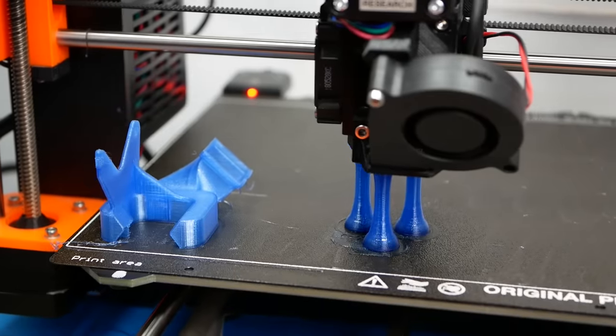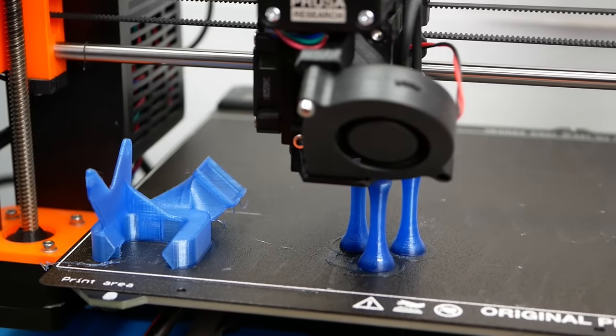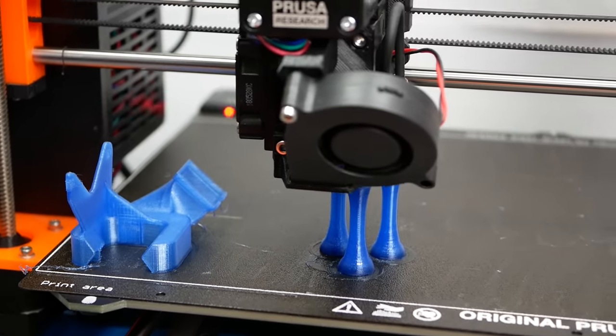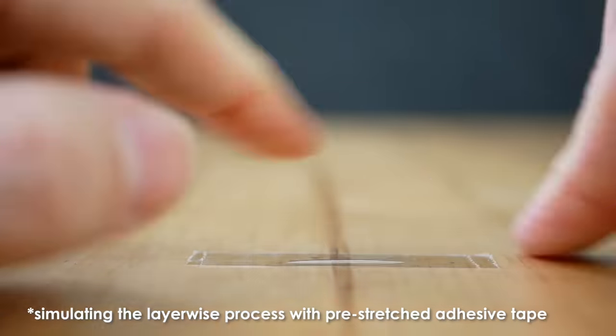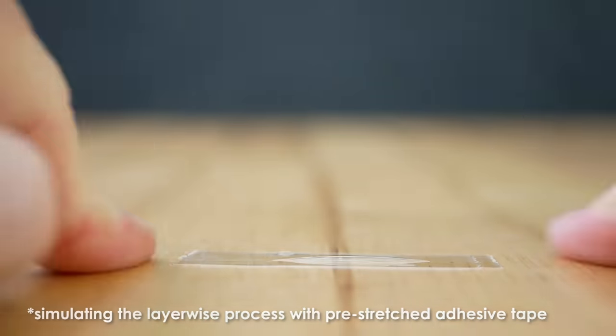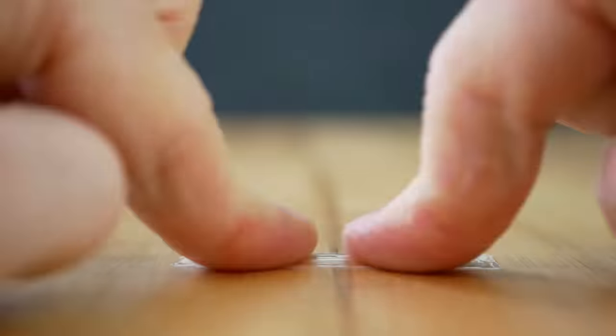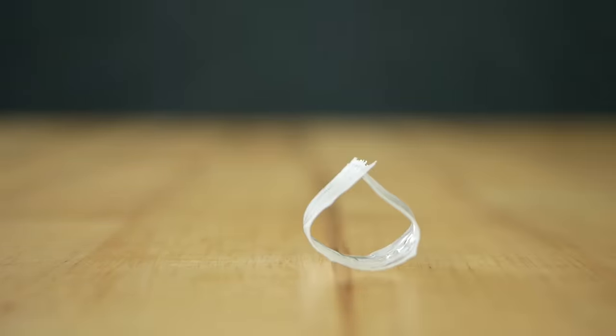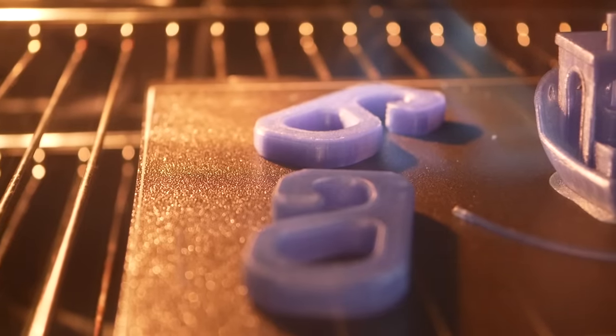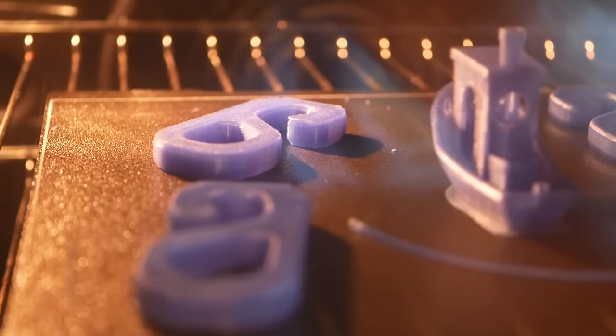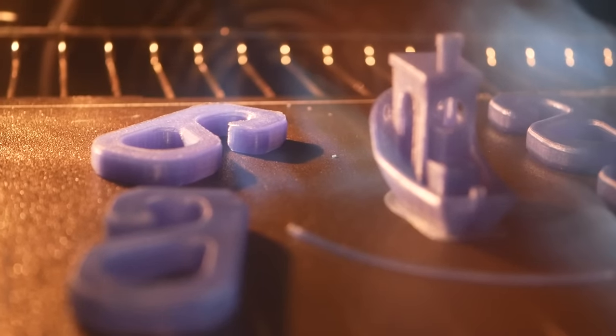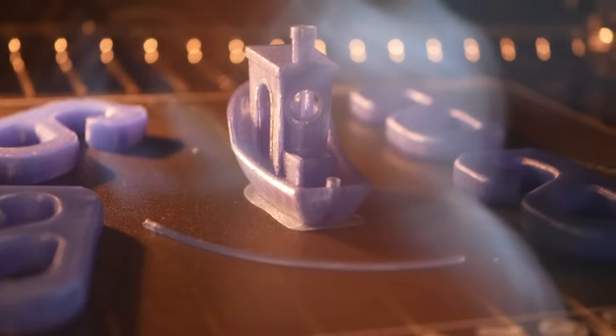Still I think what shouldn't be overlooked and what is something that I will tackle in a future video is the stress-relief annealing. Due to the layer-wise build-up process and the shrinking that happens during the cooldown, our 3D printed parts still have quite some internal stresses and these can reduce strength and especially ductility of the material. This procedure is something that can be done with basically any material, will be very interesting and will have more impact on the material properties than rather on the thermal resistance because it doesn't involve a change in crystallinity.